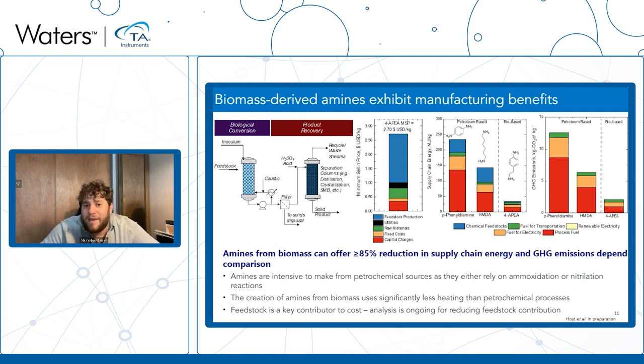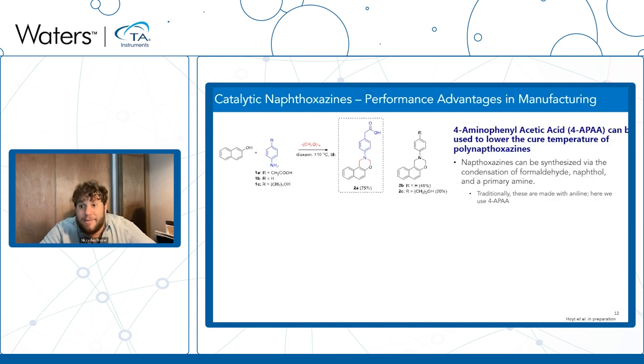Versus if you can make a bio-based amine, you can get dramatic reductions in the supply chain energy and in the greenhouse gas emissions. Additionally, when you use bio-based amines, they are cost competitive or near cost competitive with today's typical amines from manufacturers, because amines themselves are expensive to make. So here's an old slide, but analysis we've done on amines is that you can make them for about $2.70 per kilogram of material. So this kind of analysis has motivated us at NREL to look into a lot of materials that are amine-based, such as naphthoxazine resins.